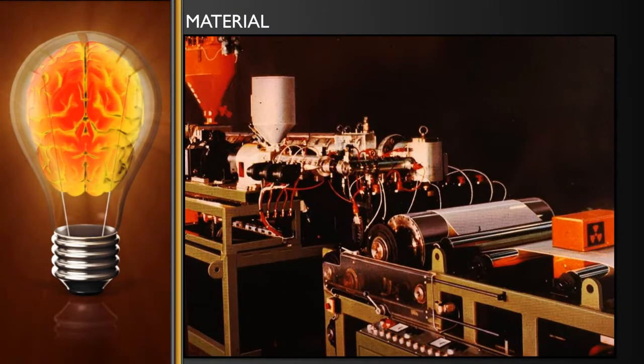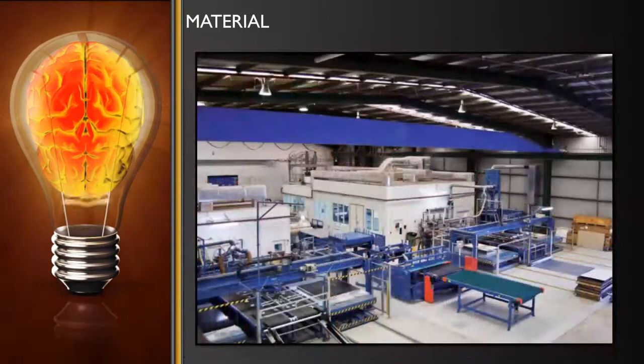But with sheet extrusion, we're able to get blends and other aspects of material which the other processes cannot obtain. For thermoforming, we're able to use materials with cap layers, UV layers and additives, co-extruded blends of materials, additives for impact and tensile strength, in addition to textures and colors. The extrusion processes are better controlled than they've ever been to be able to analyze and control the blends and mixtures of the polymers and resins.